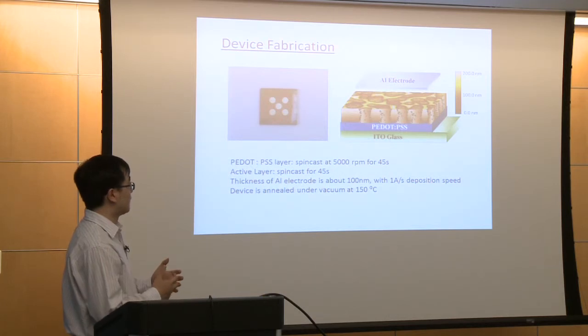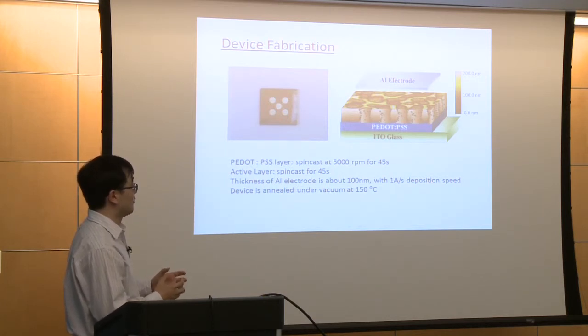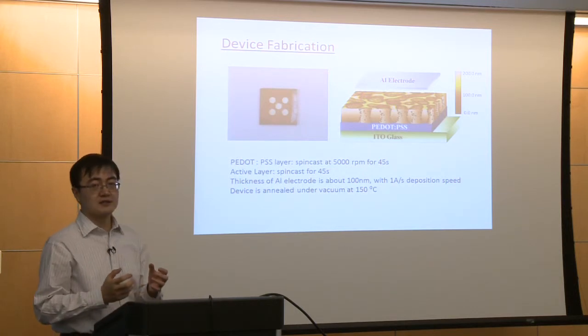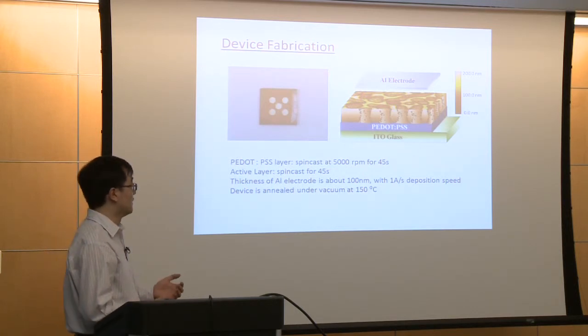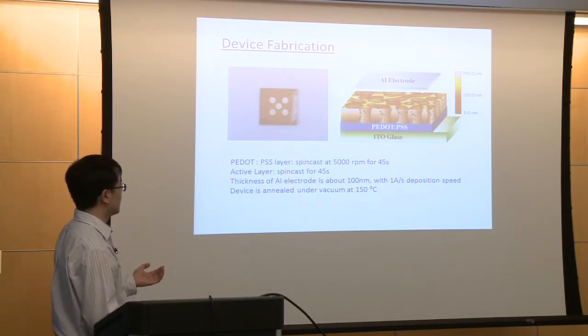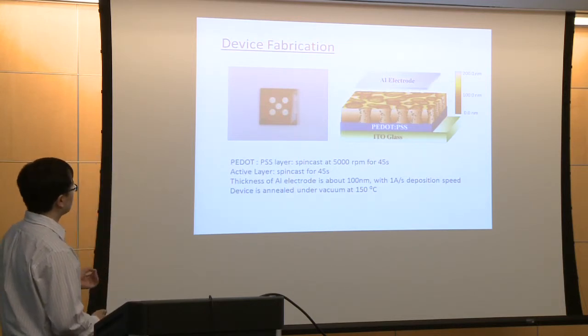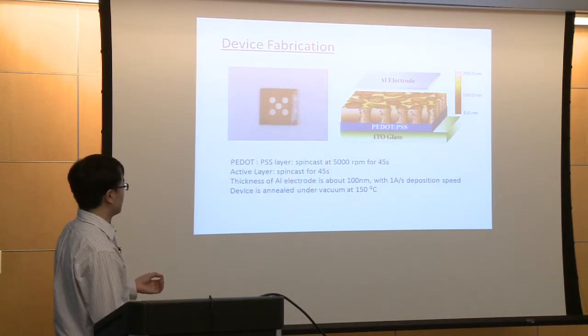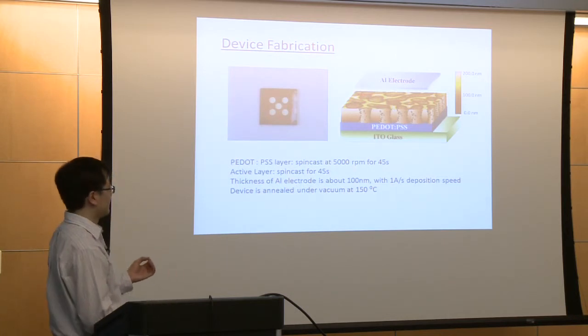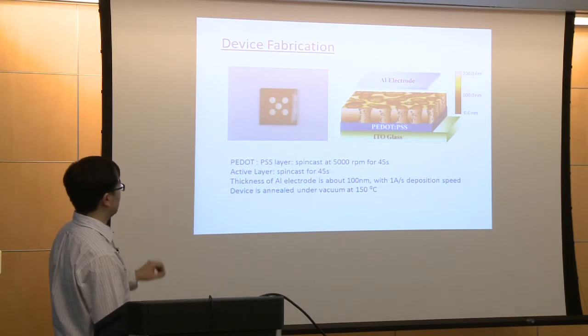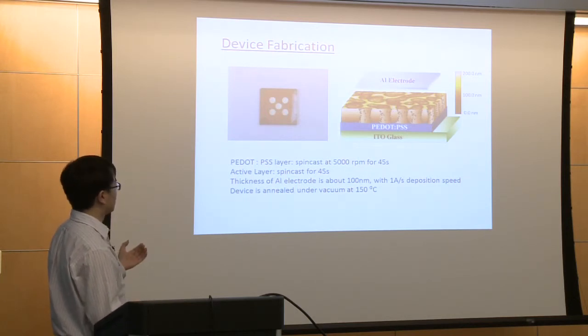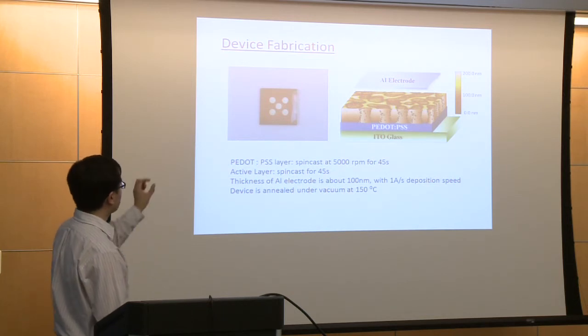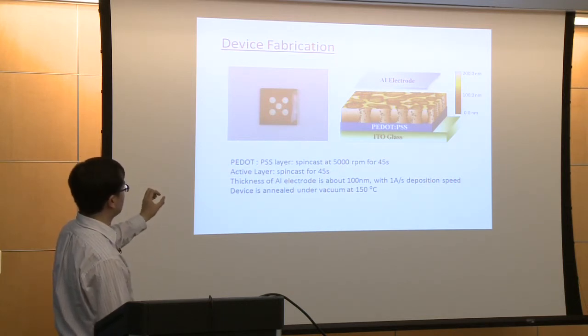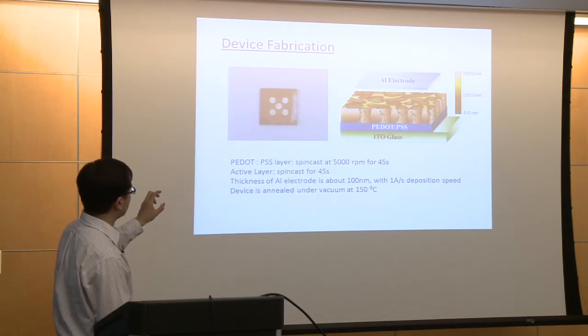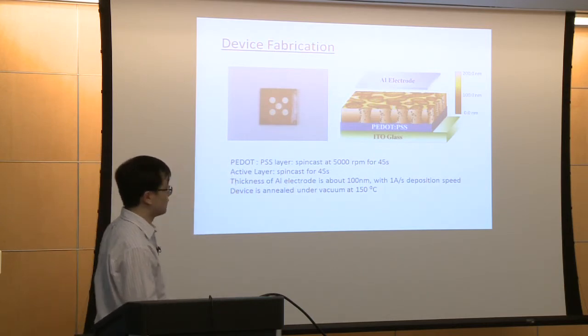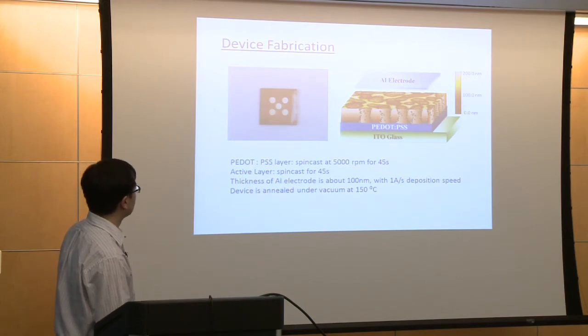So far, we have confirmed we really built the structure we want, but the next step is whether this structure really helps to enhance the efficiency of the real solar cell device. So we fabricated some devices, and this work was mostly done in Brookhaven National Lab. The left picture is the image of our real device that is ready for testing. You can see 5 big dots on the surface. Those are aluminum electrodes. And there are also 2 silver electrodes at the edge.